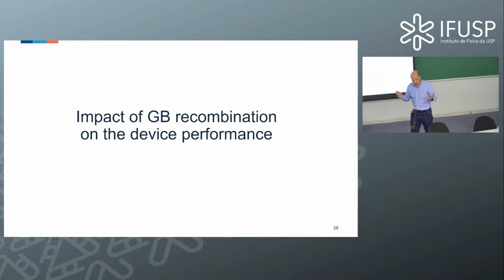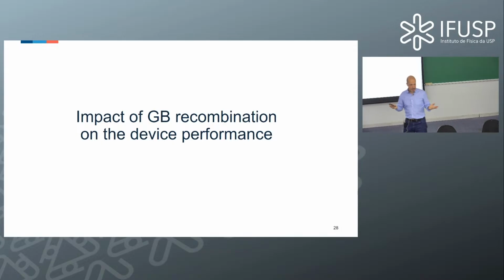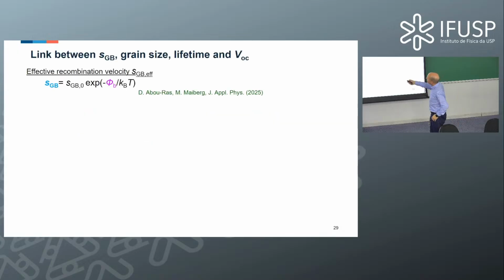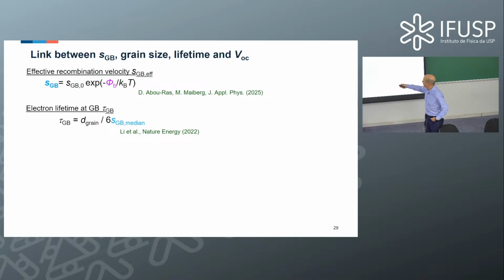Okay? So now what we have seen is everything about the recombination velocities. We have seen also behaviors in various materials, and we saw that the model can describe all of these results. Now what we want to see is, what is the impact on the device performance? And basically, I can give you this on one slide only. So we have here our equation for the recombination velocity. Then we have the equation that you already saw for the lifetime at the grain boundary. We have an average grain size. We have the median value of all these values of the recombination velocities that we measure in the material.